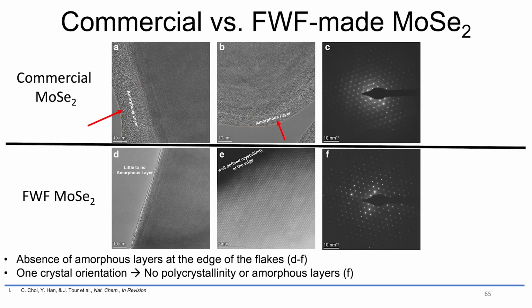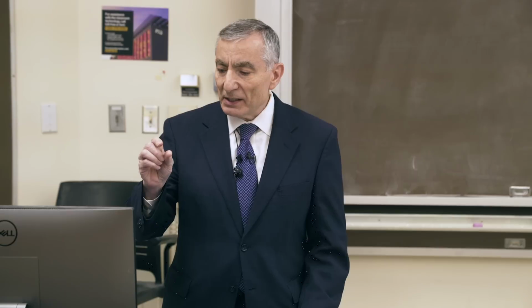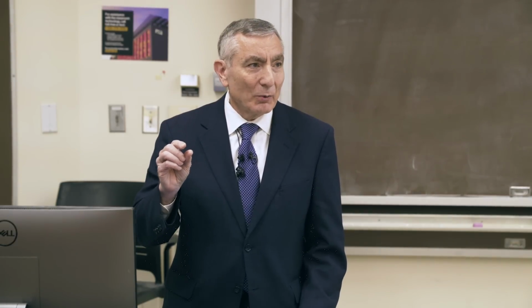And also here's commercial, for example, here's commercial molybdenum selenide. It always has a thick amorphous layer around it. Here is the flash within flash molybdenum selenide. There's almost little to no amorphous layer here. If you look at this, you have this atomic pattern right up to the edge of the material. So it's really a different material, and this is why we see these amazing properties. So it's one crystalline orientation, no polycrystallinity, and no amorphous layer. To get one little chip, one of our reviewers said you're going to have to compare it to commercial material. We had to pay over $600 for a tiny little crystal of commercial material, and we were making grams at a time in our lab using this methodology.